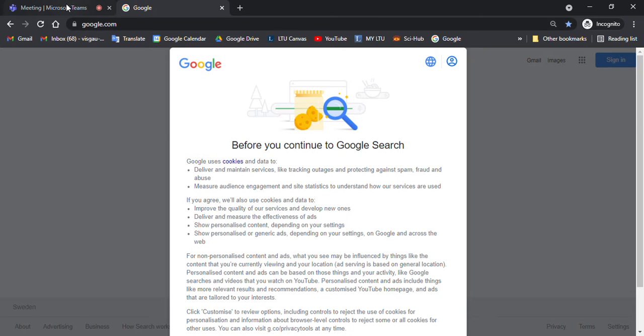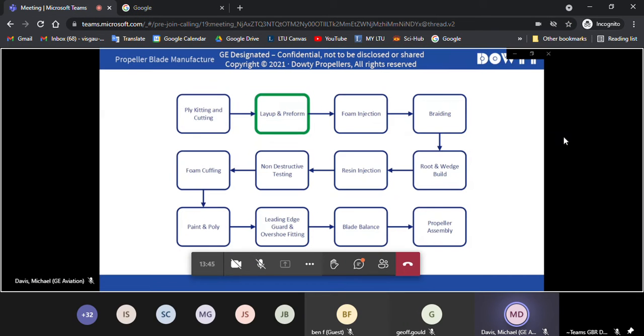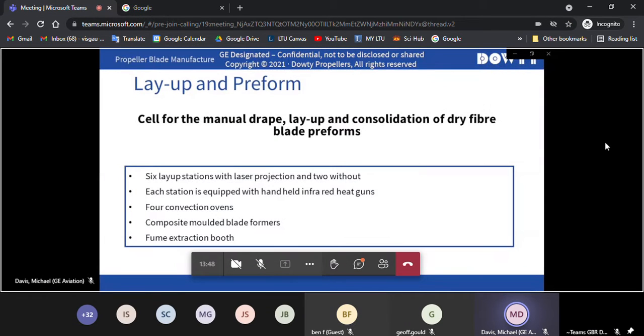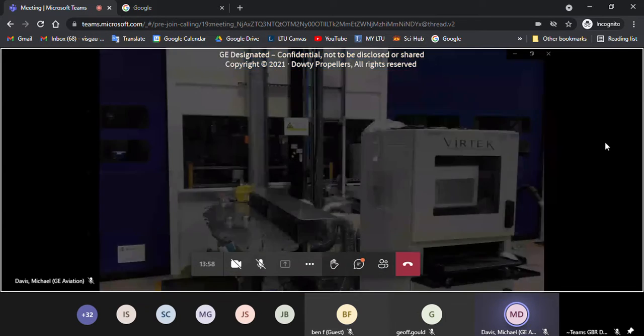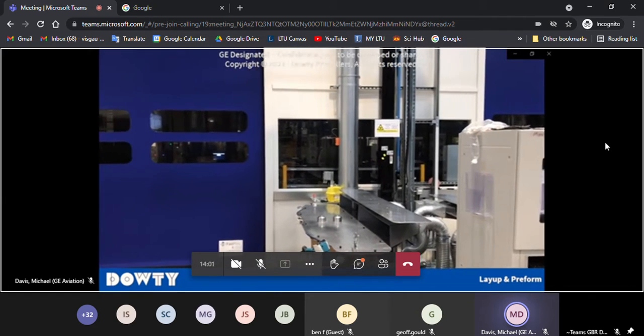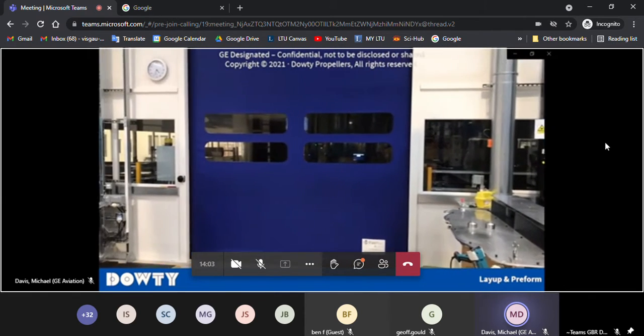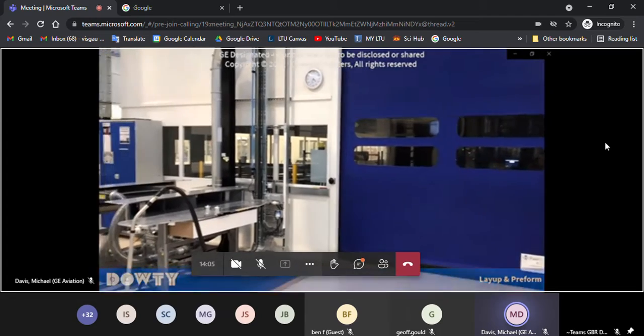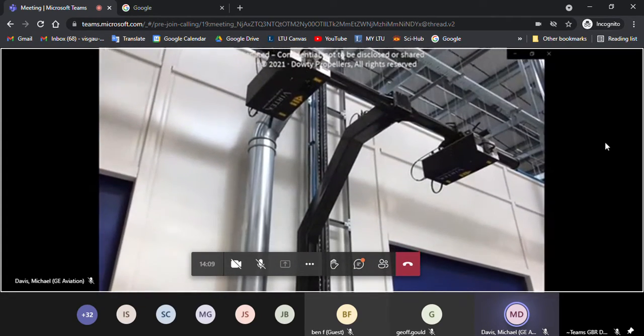Dry fiber materials have been cut into plies of the correct orientation and shape for producing composite propeller blades. Those plies are kitted and then sent up to the layup and preform cell, which we'll walk around now. So now we're looking around the preforming cell where individual dry plies are stacked up and formed to produce a propeller preform. So we start to see a blade taking shape.